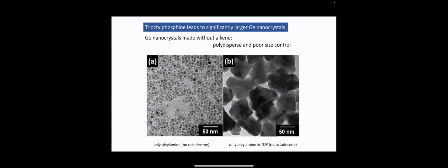So these heat up reactions work pretty well, and you can make relatively monodisperse nanocrystals up to about 10 or 11 nanometers in diameter. And once you try to go above 11 nanometers in diameter, we just found you couldn't, for whatever reason. I mean, it's just the combination of the kinetics and the bonding of the alkene, and we tried a bunch of different reaction conditions and doing hot injection and all of that sort of thing. Even with hot injection in the oleylamine, you can form nanocrystals, but they only grow to a certain size. So what we found is that we can use trioctylphosphine to make significantly larger germanium.